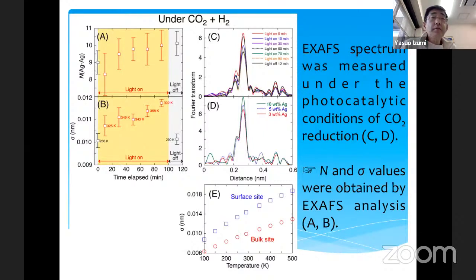Basically, how much silver is around your silver. So silver nanoparticle size is reflected, but also, somewhat more advanced, a technique is used here. Maybe I do not talk about everything, and it's somewhat complicated, but very interesting, because this vibration factor is associated with the coordination number. Coordination number is here. A slight increase in coordination number means a very slight increase of silver nanoparticle size growth during photocatalysis was observed, but